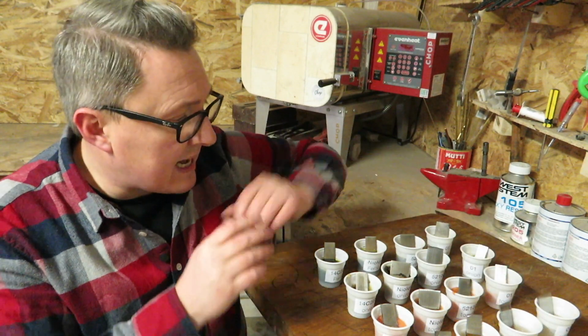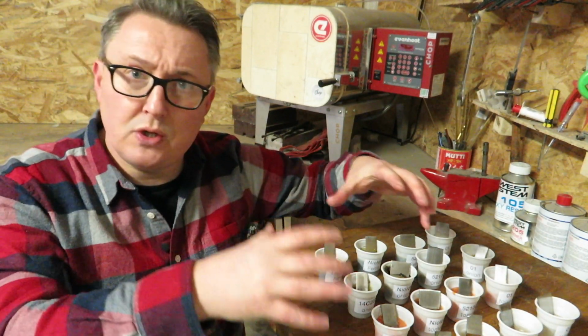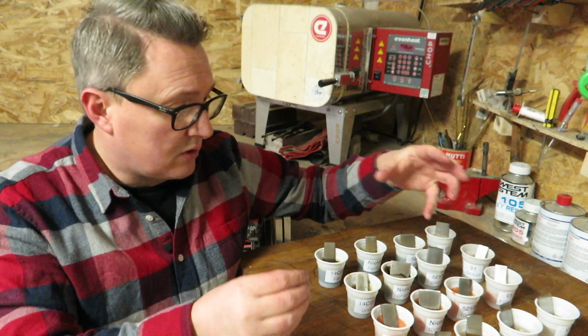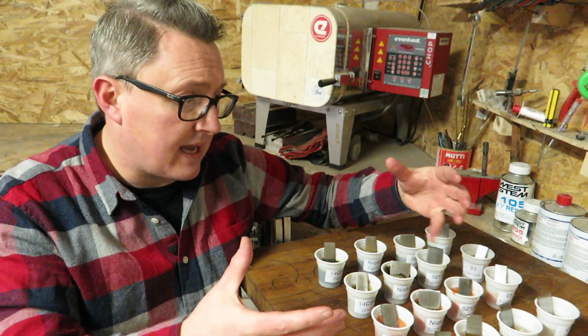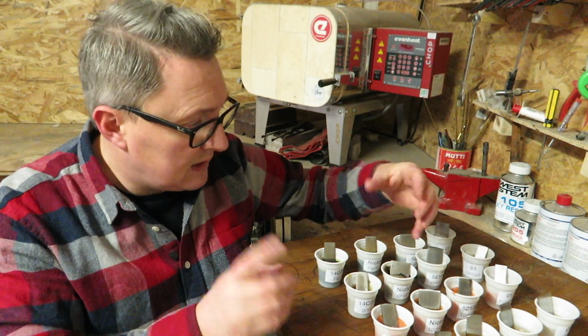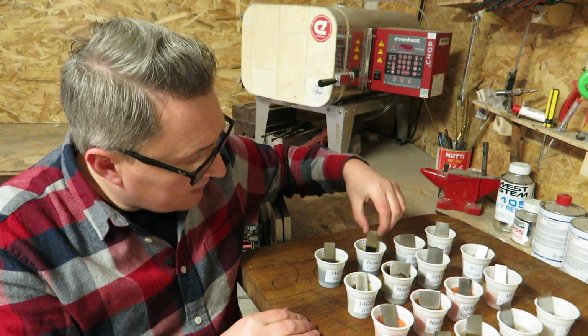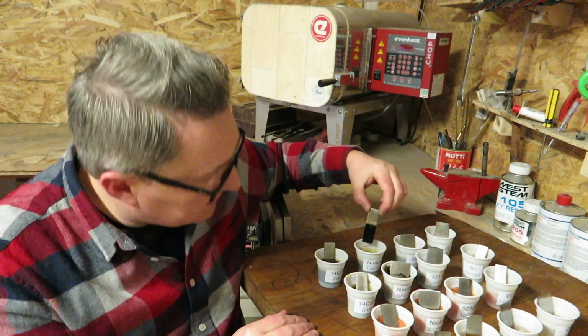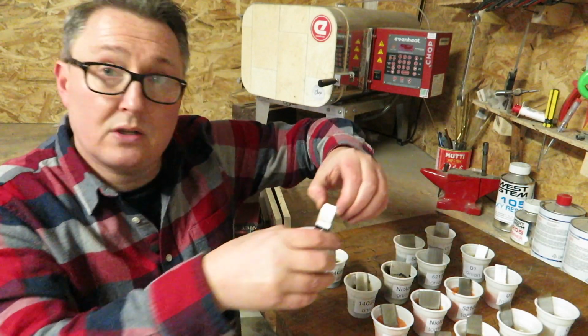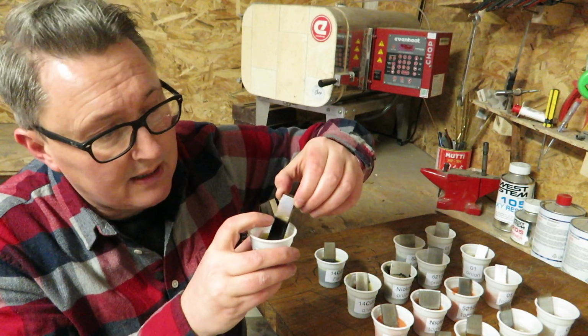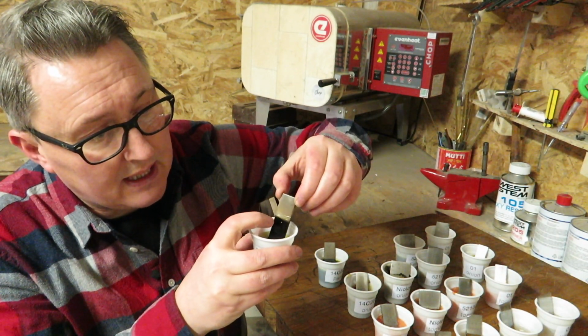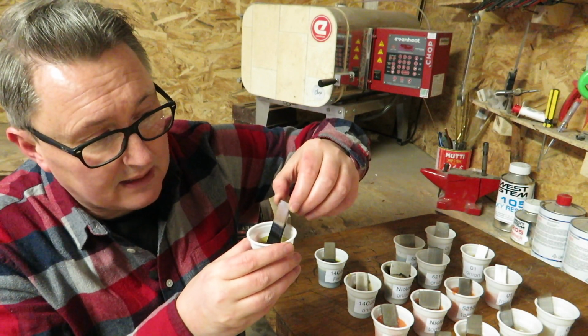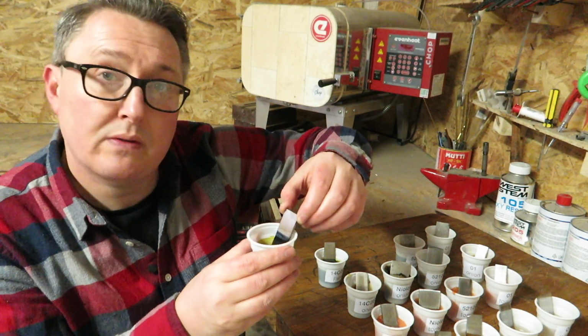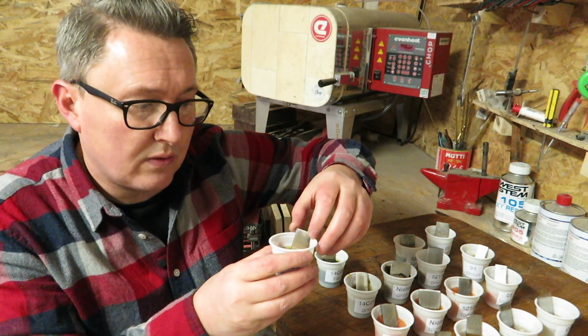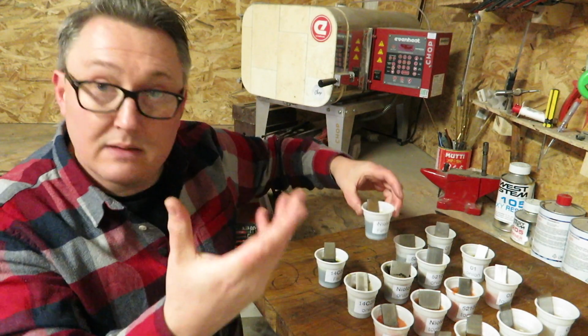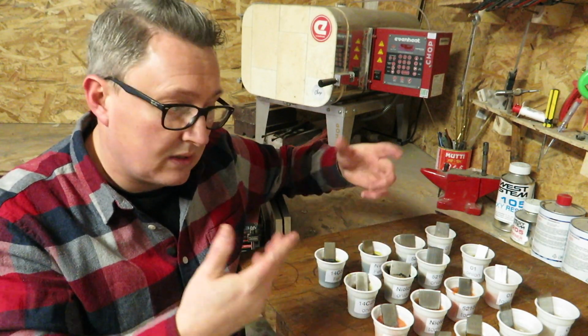Now, I think what has happened is these have been submerged in their liquids, so they haven't really had time to oxidize. They haven't been exposed to any oxygen. And you can see that, and let's have a look. This is the Niolox, which has been in the ferric chloride. It's obviously very dark because it's been in ferric, but where the surface of the liquid hits the steel, that seems to be where most of the corrosion is. So that's due to the oxygen. It's mixing with oxygen, so it's oxidizing and causing the rust.